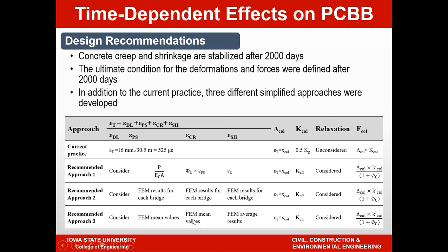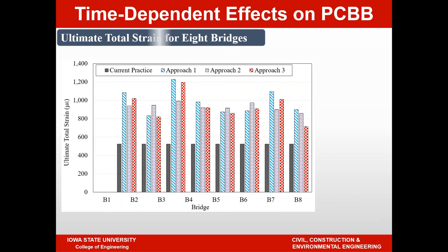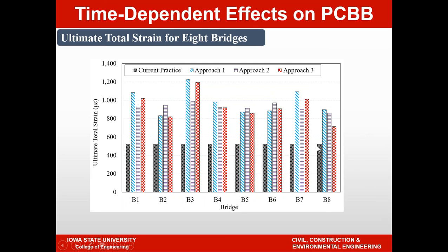So that's one direction to go. As I said before, we could also include this value along with some plus standard deviation to get some conservative results. But nevertheless, we are comparing these three different methods with what the finite element itself predicted as strains. So you can see here that the total strains are compared for, again, the current practice is expected to be lower because of the assumption, and we should include the pre-stressing strain here. But if you look at the three methods that we're looking at, they actually came out pretty close to one another. In some cases, you see that methods one and three are closer than two, but in some cases you see that approaches two and three are closer.